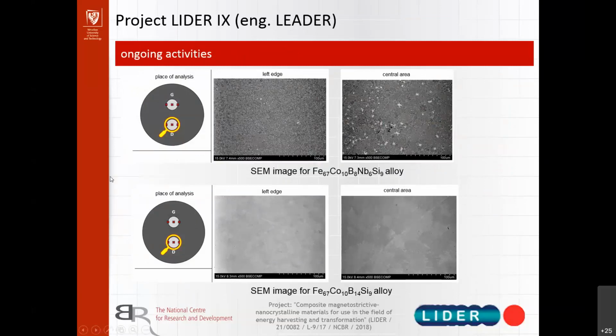So you can see where we were taking these images from those materials: the left edge, the center, and the right edge. The left edge and the right edge are very similar, so this is why I just show you the left edge and the central area of each sample. So you can clearly see that those two alloys are very different.